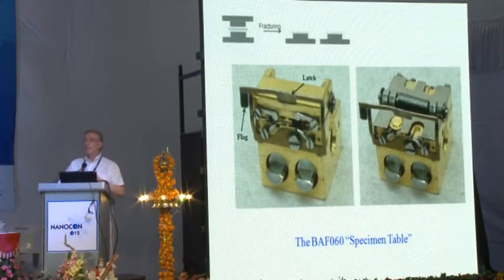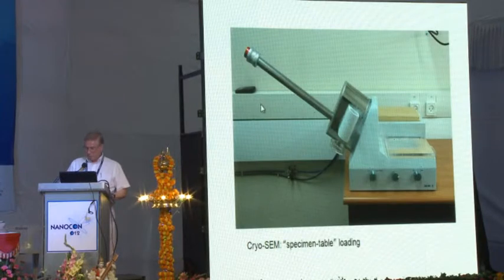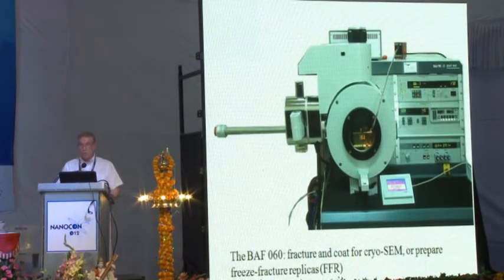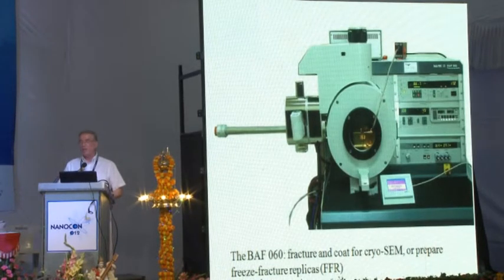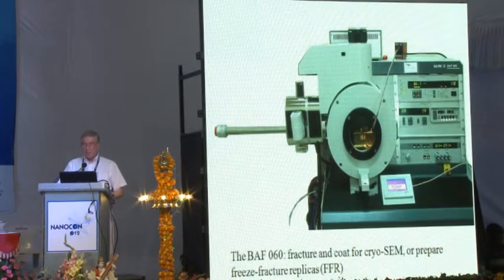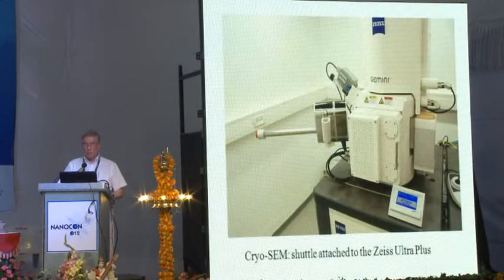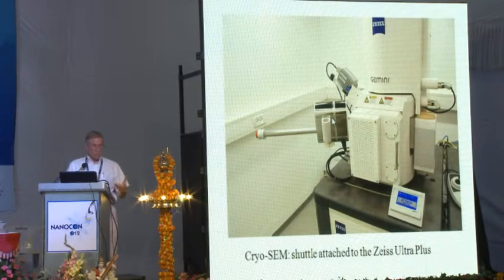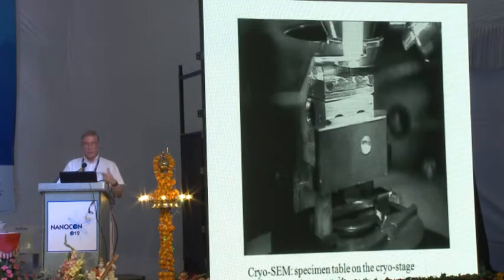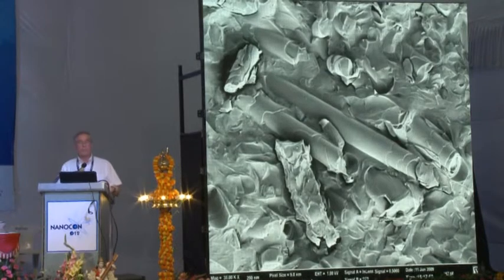This is the little specimen holder that allows you to actually take the sandwich and fracture it. The fracturing itself is done in a special apparatus at very high vacuum and very low temperature. The specimen then is transferred with the shuttle. This is the shuttle to the electron microscope. Now you can see the shuttle attached to the electron microscope. The shuttle is evacuated and kept at low temperature, so the specimen can be introduced without any harm into the electron microscope. And this is what you see.